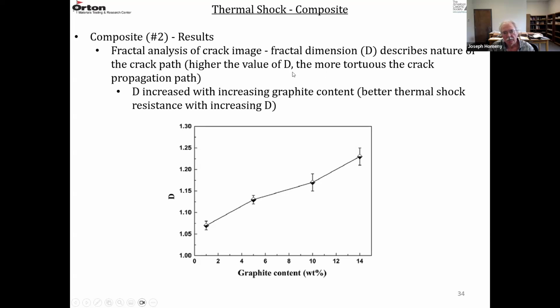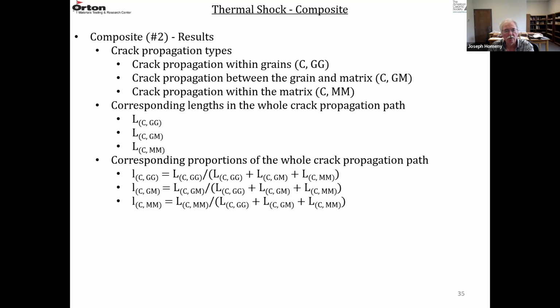So the higher the D value, the more tortuous the crack path, it should have higher thermal shock resistance, the higher work of fracture. So D increased with increasing graphite content. So that predicts better thermal shock resistance with increasing D. So this is that fractal dimension D versus graphite content, and it increases with graphite content, meaning that the crack path is more tortuous. And the more tortuous the crack path, you do that by controlling the microstructure, the better the thermal shock resistance.